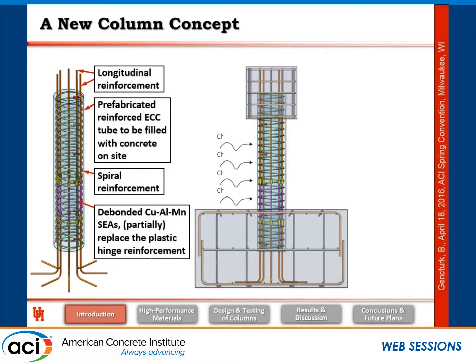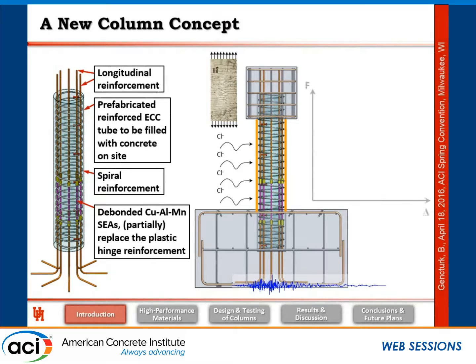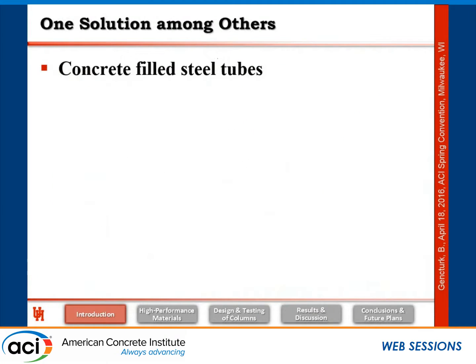So what is the advantage of this concept? If we think about durability, if there's chloride attack on the column, this ECC has much higher crack tightness. Even in cracked state, it has much lower permeability compared to a conventional concrete. And the second thing is, in this combined hazard situation, the earthquakes. So when there's an earthquake, hopefully these superelastic alloys in the plastic hinge region will make this column behave like this flag-shaped response with some energy absorption but no permanent drift, so that you can still use the bridge immediately after an earthquake.